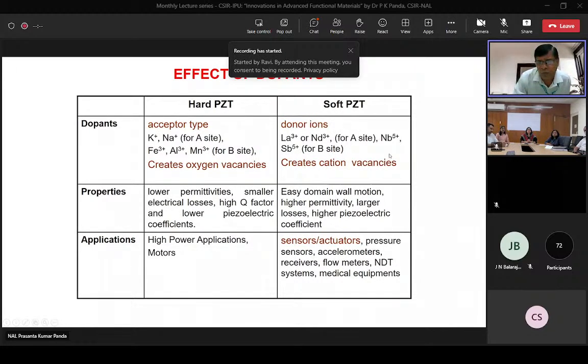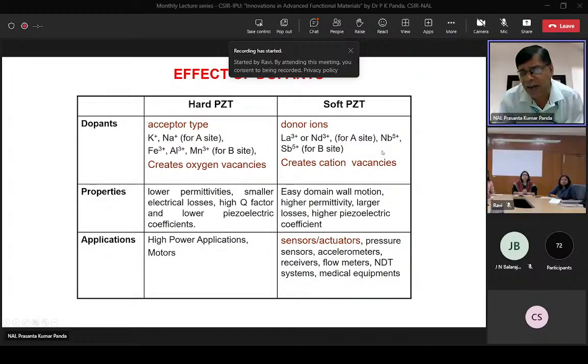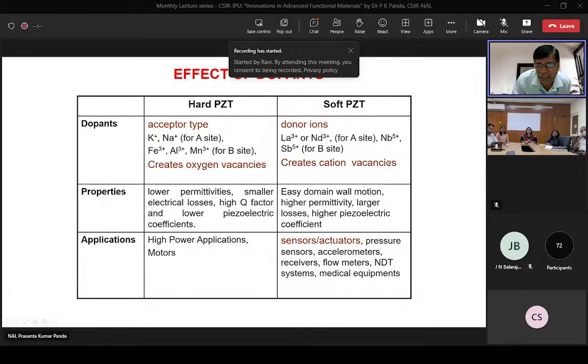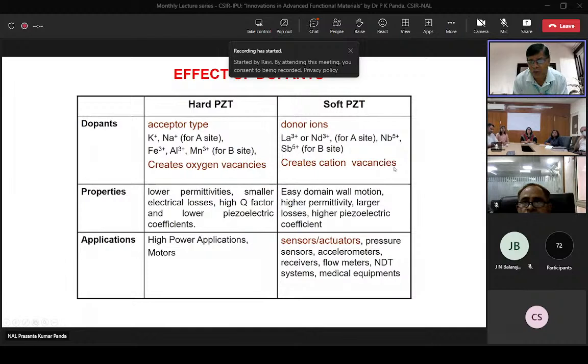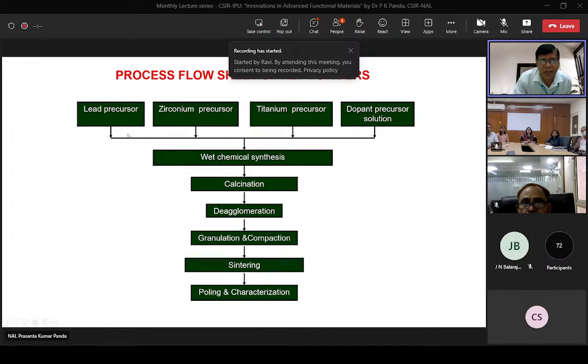In our case, you have to go for soft dopants, wherein in the ABO3 structure, you select a cation of one valence higher, so that we create cation vacancies. And these cation vacancies also help easy domain wall motion. So this is the science behind piezoelectric material, a little bit. And when you take various precursors, you have to use a wet chemical method; this is very important. We should not go for the mixed oxide method. The chemical method will help in homogeneity of mixing when you are dealing with multi-component systems, and then calcination. Some are at 1100 plus, and de-agglomeration after cooling, then granulation and compaction to make pellets, and after sintering we have to do polishing, poling and characterization.